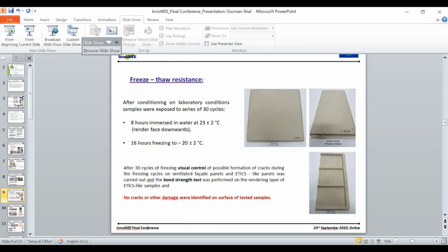For the freeze test, we expose samples to 30 cycles from -20 degrees C to 23 degrees C. And as you can see also from the figures, we have confirmed that after 30 cycles of freezing thawing, there are no cracks or any damage on the surface of the samples. So no cracks were identified. We can say that the samples are freeze-thaw resistant.